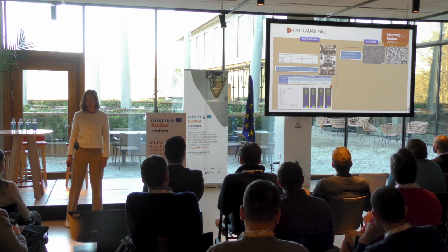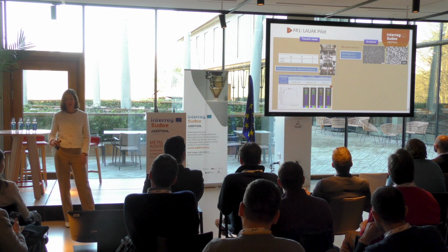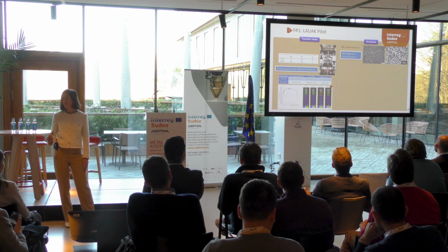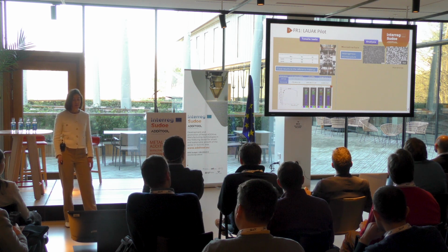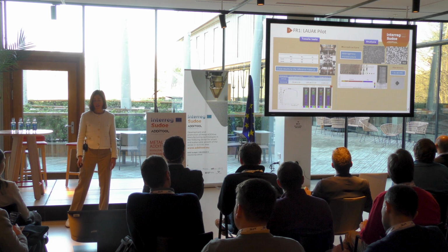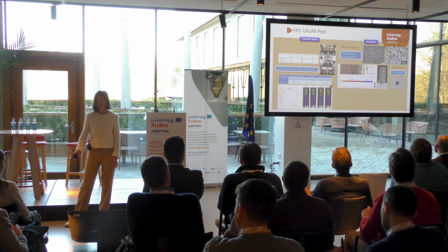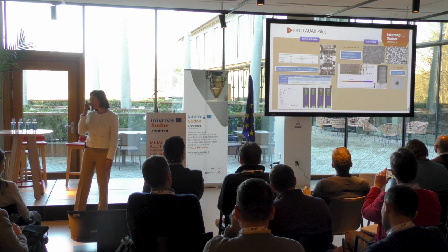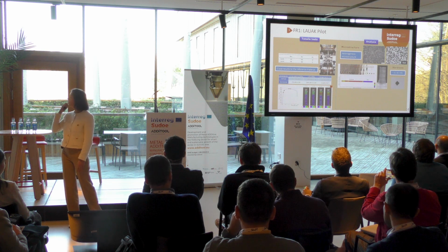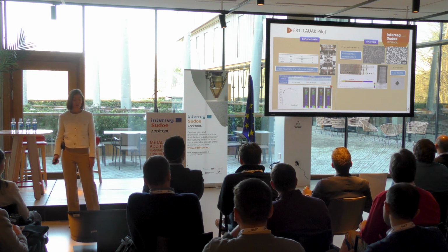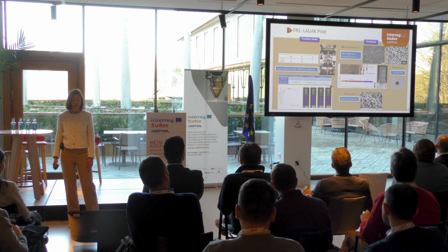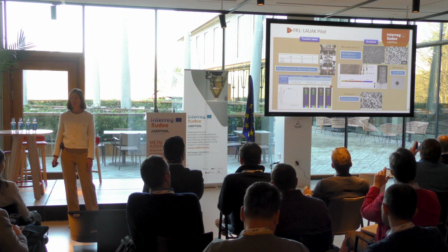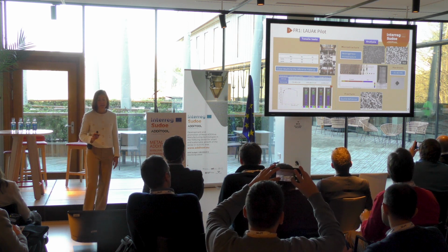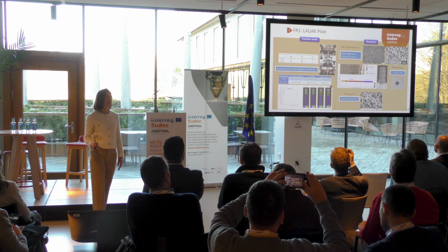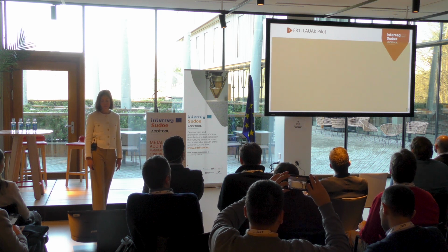Regarding microstructure, we saw different microstructure depending on the zone. So we had heterogeneous microstructure, but looking also at the tensile results and hardness, which are very similar to the reference material and quite homogeneous, and the fracture that was ductile, we conclude that this heterogeneity didn't affect the overall properties.